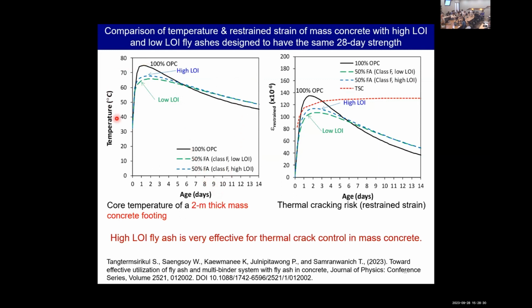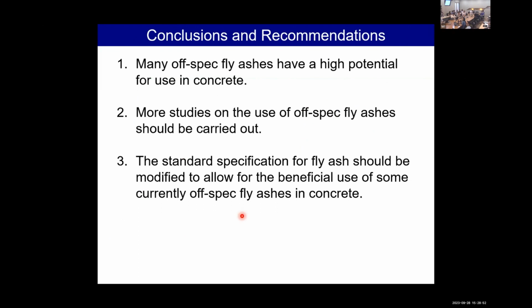In this case, the results show that the temperature of the high LOI fly ash is lower than OPC, and the restrained strain of the high LOI fly ash is lower than OPC. So it means that high LOI fly ash is very effective for thermal cracking control in mass concrete.